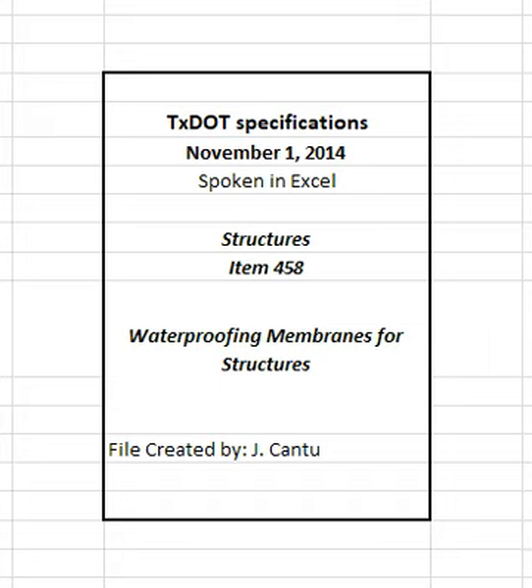3.5 Type 4. Unwrap the roll of waterproofing and press the adhesive surface into contact with the concrete horizontally. Secure the free end and then unroll slowly, using hand pressure to smooth the membrane into place and help make a tight bond with the concrete. Overlap adjacent strips a minimum of 1 inches over the previously laid strip. Backfilling may be started as soon as the initial horizontal strip has been applied.